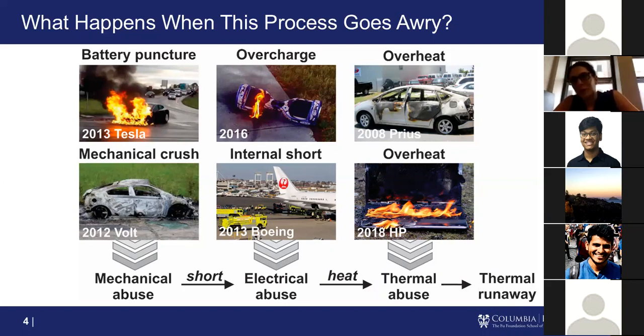The other issue with these batteries lighting on fire is that lithium itself is pretty reactive. If you look at where it falls on the periodic table, lithium metal is a pyrophoric material. So whenever these things catch on fire, they're around a lot of organic electrolyte. It's a pyrophoric material, and the fire doesn't actually behave like a normal fire. So they're actually very hard to put out. Even if you do get the fire put out, it can spontaneously reignite, and they burn at a much hotter temperature than a normal electrical fire, say. So it actually poses a great risk to the people who have to put these fires out, so the firefighters, and we'll talk a little bit about that as well.